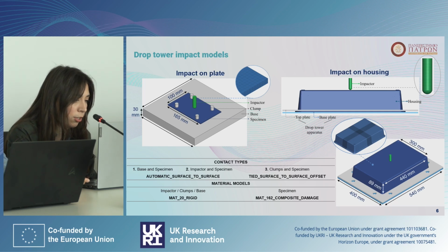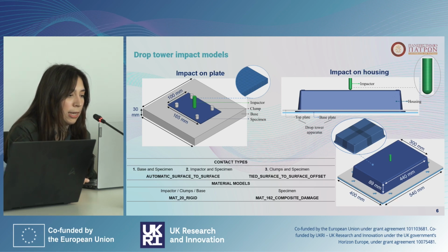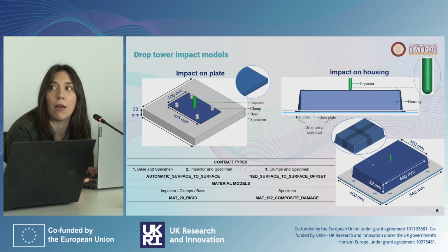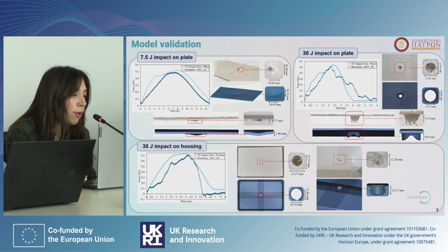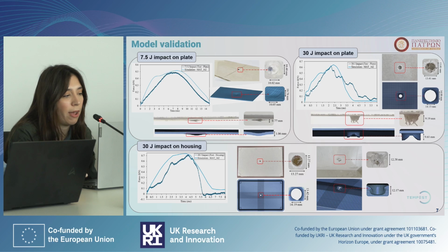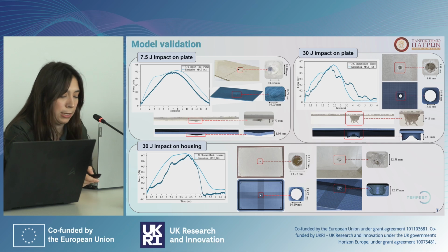initiation. The second drop tower simulation model replicates the impact event of a projectile striking the SMC composite housing. Overall, the simulation shows very good agreement with experimental results in terms of damage size, shape, and deformation depth, confirming the model's validity. It reliably captures damage patterns and force responses across different structural configurations, both plates and housing, demonstrating its applicability for predictive analysis in composite impact scenarios.